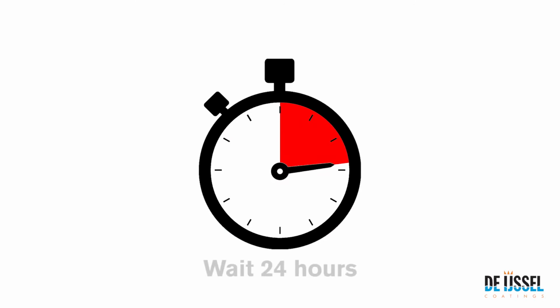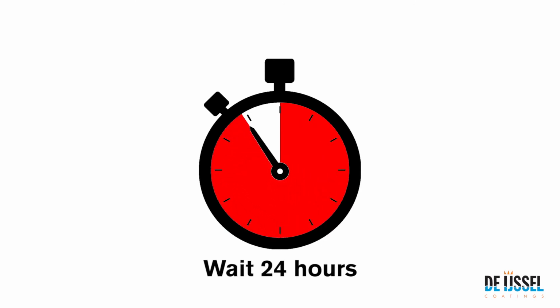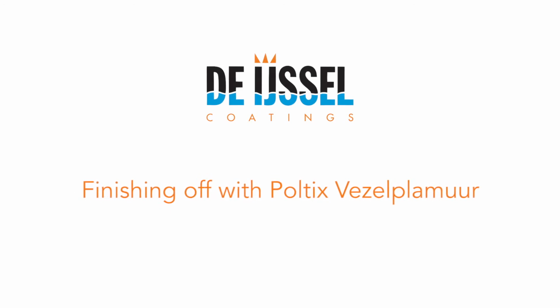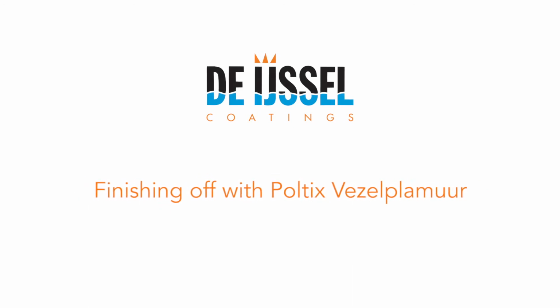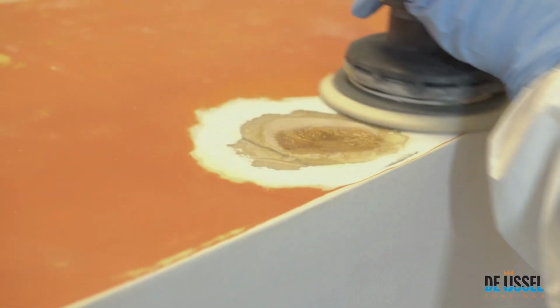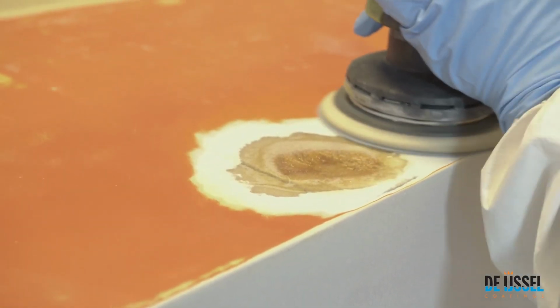After 24 hours drying, the surface can be sanded with P120 sandpaper and degreased. The last bumps can be filled with Poltix vezelplamuur. After sanding the surface, it can be finished with Amopox HB coating or double coating.